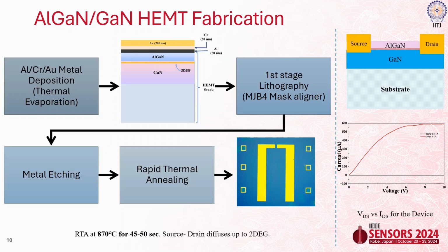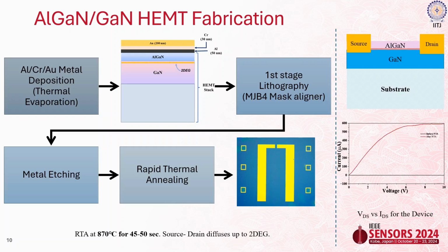What it does is that, if you see on the right side, the source and drain patterns we have made are on the surface. So we are annealing this whole thing at 870 degrees for 45 to 50 seconds. That leads to the source and drain diffusing up to the 2D electron gas that is located around 18 to 20 nanometers below the surface. Before this, the current is very small, almost open. After we do the RTA, we see a proper transistor-like current.